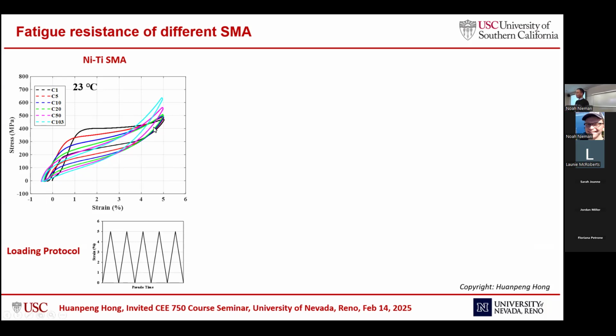For the nickel titanium shape memory alloy at room temperature, this C means cycle. The first cycle has 100% strain recovery, and as the loading cycles increase, the yield stress decreases. The good news is that the strain recovery has almost no change. After around 100 cycles, when this material fractures, it still exhibits 100% strain recovery capacity.